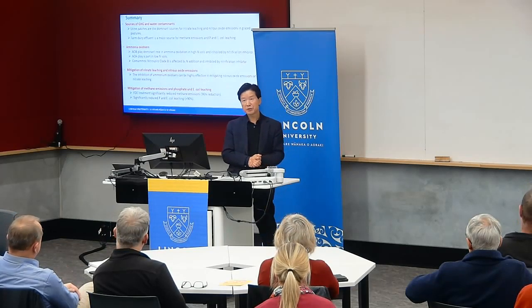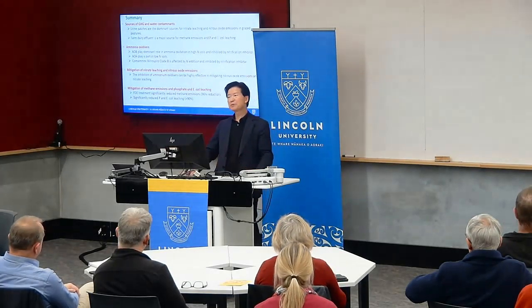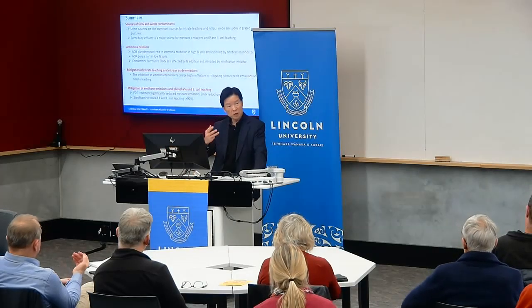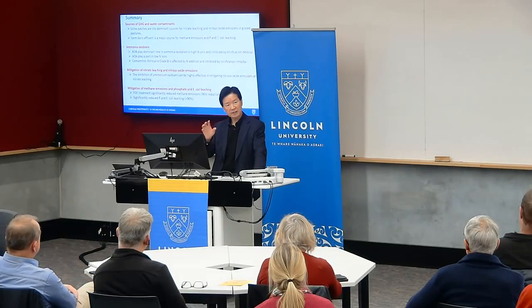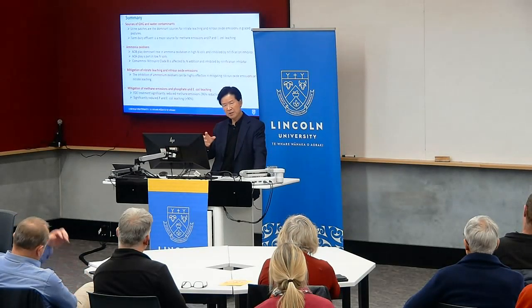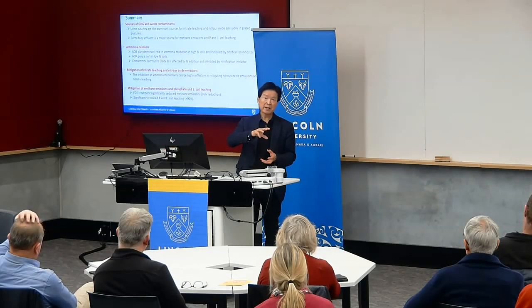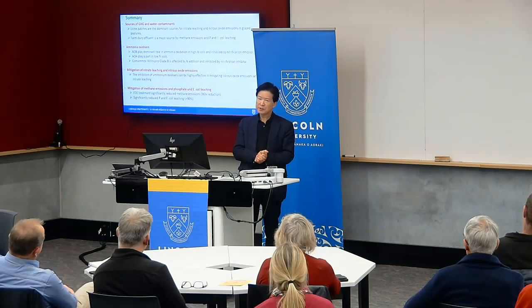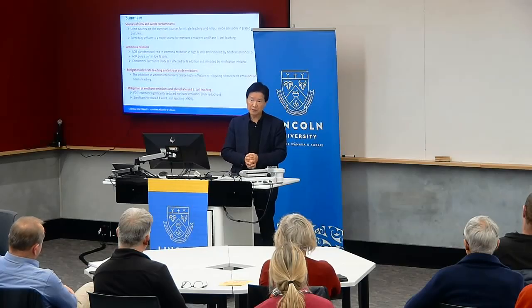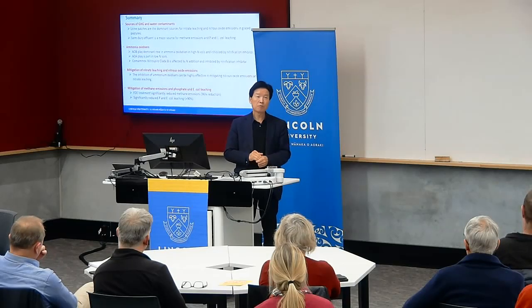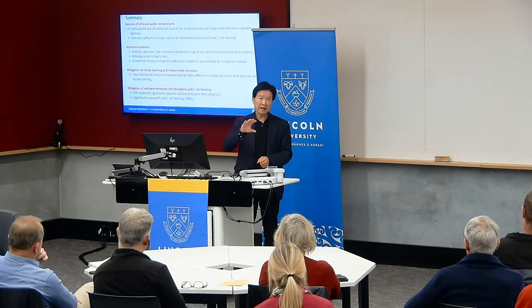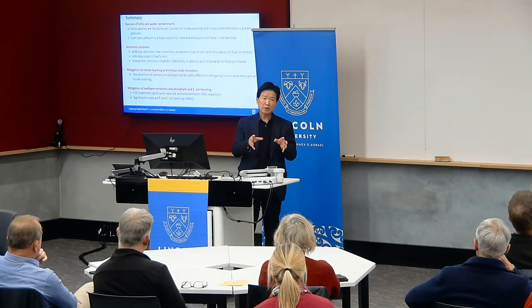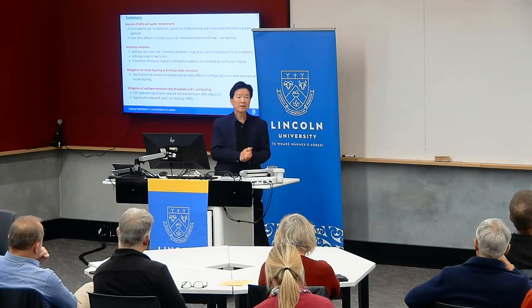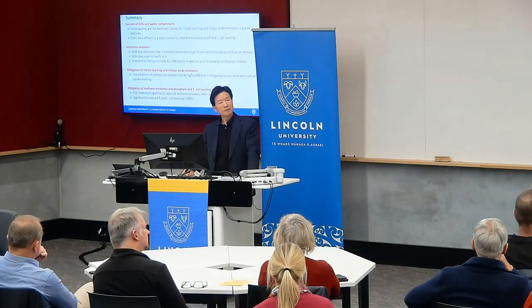That's a very good point. Actually, we looked into this aspect with DCD as well. I think the difference with these nitrification inhibitors is that we are trying to find one that doesn't kill the bacteria. We're trying to find a compound that only blocks the active site of the enzyme, so that essentially the microbes lay dormant. With DCD, we did not find much resistance. And the current one that we've just developed has what we call a suicidal binding mechanism. We will certainly look into it. Hopefully it wouldn't happen. If it's like an antibiotic or bactericide, it's probably more likely to develop resistance more quickly. Whereas if it only targets the ammonia oxidizing enzyme by blocking the active site, it may not develop so quickly. That's our understanding. Very good question.